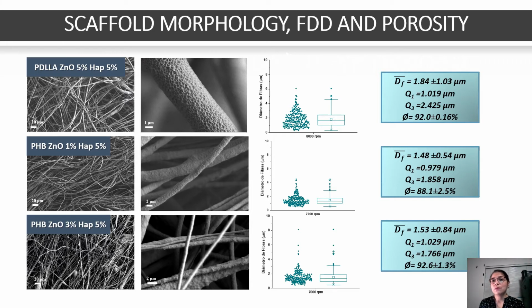In relation to PHB, the micrograph shows 2 systems with different concentrations of zinc oxide. As can be observed, a higher concentration of zinc oxide promotes the formation of fibers with less regularity, as well as a higher roughness. These characteristics produce an increase in the fiber diameter dispersion. Finally, the scaffold presented porosity above 80%, which represents an advantage for the application.